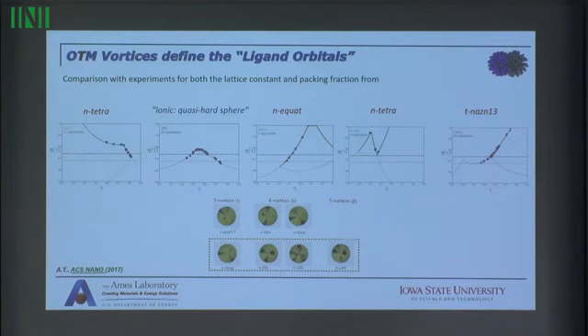So what you can do now is use these things to combine them and try to find new structures, and this is something that I will not discuss here. But basically, what we've shown is that, for example, we had a talk this morning about nanocrystals or colloids with valence. What we have here is the ability to spontaneously generate valence. So for example, we have 3, 4, or 5-fold. This is 3-fold. This is 4-fold. So these nanocrystals have the ability to spontaneously generate valence and have, for example, a 4-fold or a 5-fold or a 3-fold, depending on the environment.